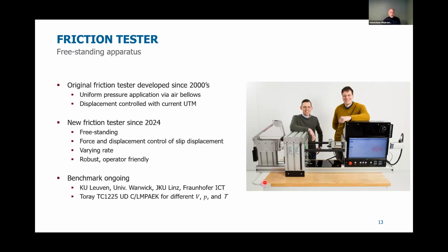And we're currently benchmarking this machine against our old friction tester and also friction testing activities that are going on at the KU Leuven, University of Warwick, Johannes Kepler University in Linz, and Fraunhofer ICT. And we've chosen here Toray low melting carbon PEEK, and we run a set of experiments at varying speeds, pressure, and temperatures. So that was friction testing, as to describe one of the mechanisms.